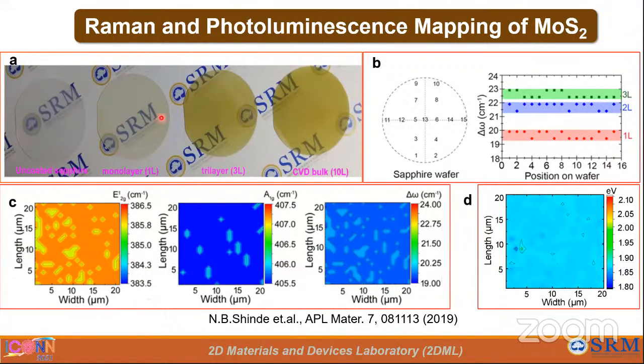How do we identify whether it is uniformly coated or not? We recorded Raman spectra at several places, more than 15 times, and we are getting almost uniform results all over the area. Then Raman mapping shows the spatial homogeneity of our sample. We mapped particularly the A1g peak, and all over the sample only 0.5 centimeter inverse changes in the spectra. That means our sample is uniformly coated on the sapphire wafer.